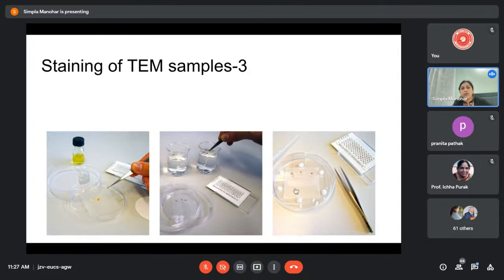And then after we finish staining, we put the grids back in the grid box. It is preferred that after staining, we wait overnight so that the stains dry and there is no water content on the sections, because remember, we don't want water in the transmission electron microscope. But we have to make sure that once we stain with lead citrate, it is not exposed to CO2, because even after all the sectioning and staining has been done, the grid can react to CO2 present in the environment and cause precipitate.